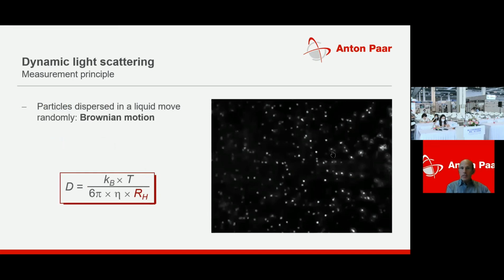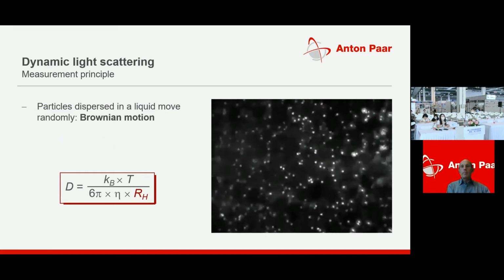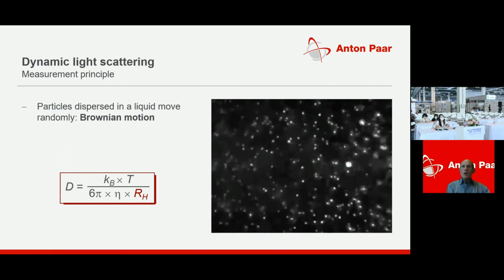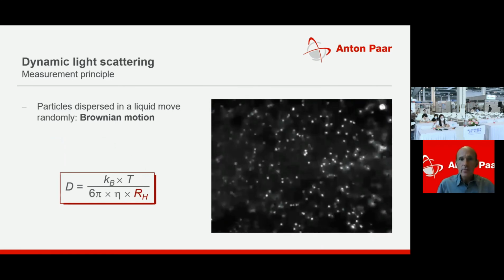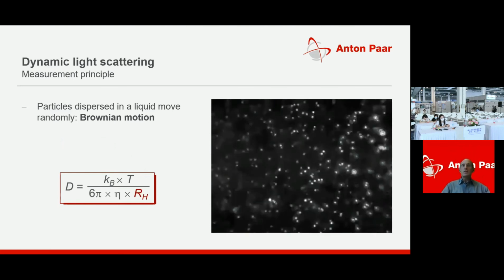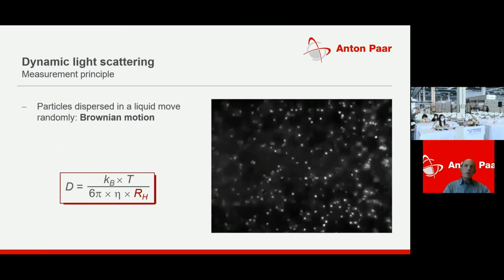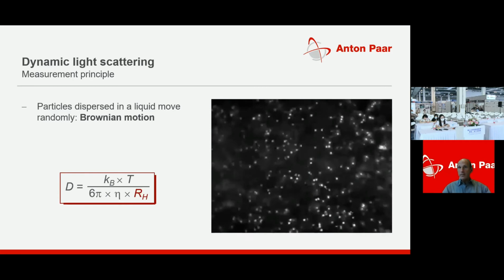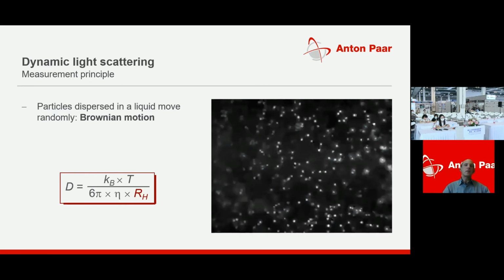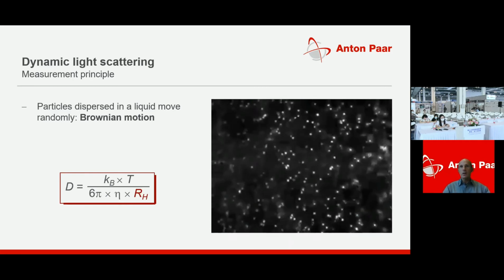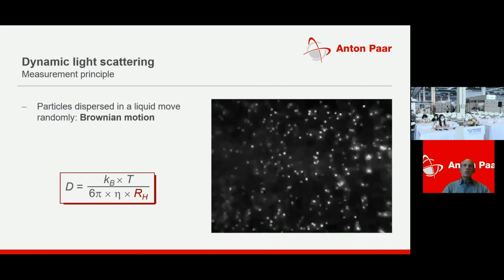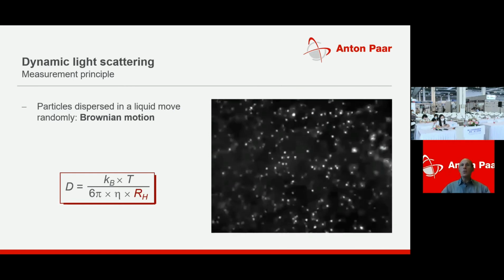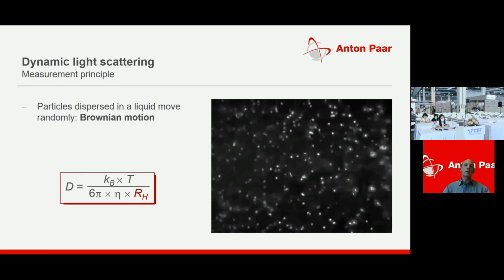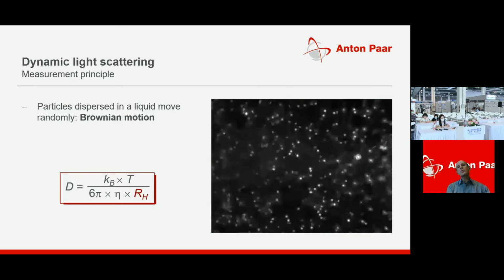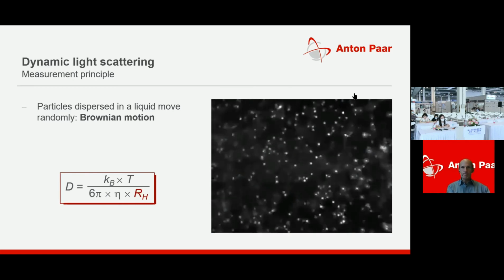The measurement principle of dynamic light scattering for particle size analysis relies on Brownian motion, which is a random motion of particles dispersed in a liquid. The primary parameter determined by dynamic light scattering is the diffusion coefficient of these particles, which is related to the hydrodynamic radius or hydrodynamic diameter by the Stokes-Einstein equation.